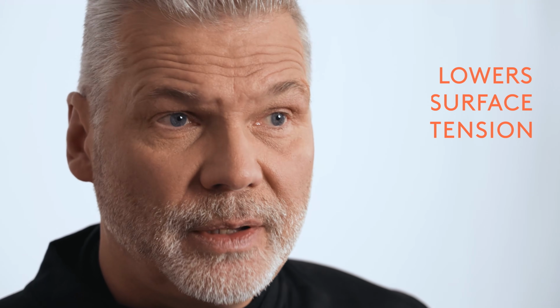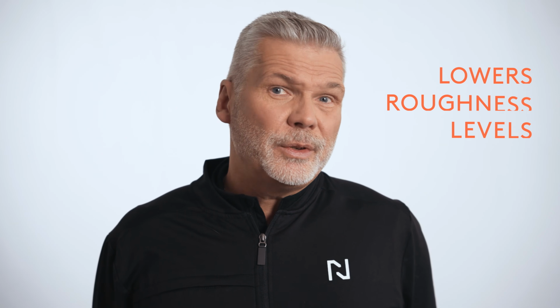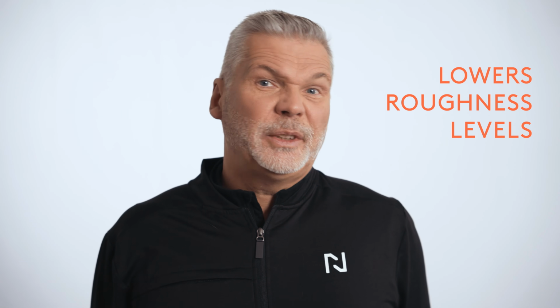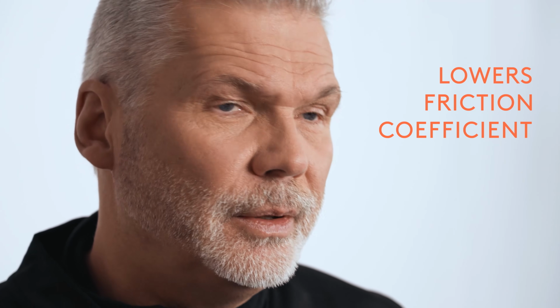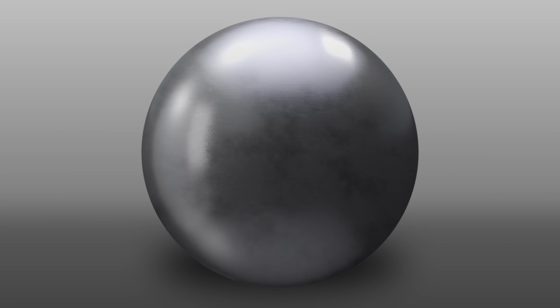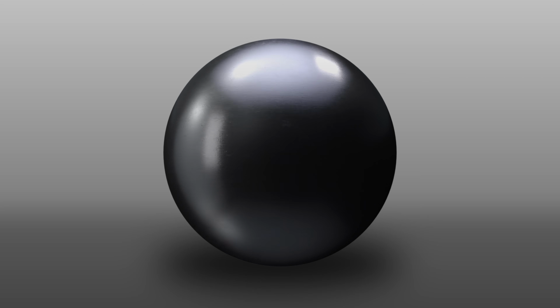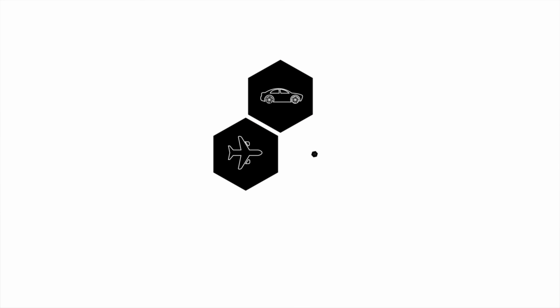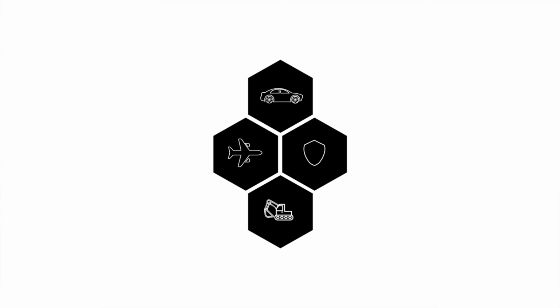It improves corrosion resistance, lowers surface tension with the presence of oxyhydroxides, and lowers roughness levels obtained after nitriding or nitrocarburizing. It will also lower the friction coefficient. And also, a post-oxidized surface will look great when oiled, with a very dark black finish. No wonder post-oxidation has many applications in hydraulics, armament, the automotive industry, or in mining equipment.